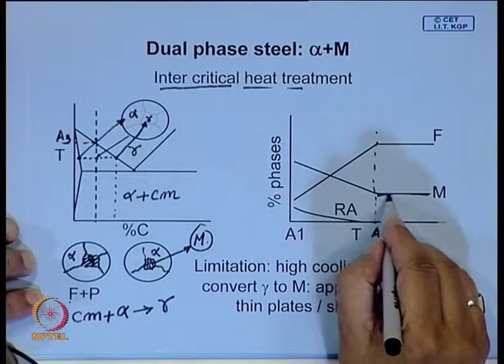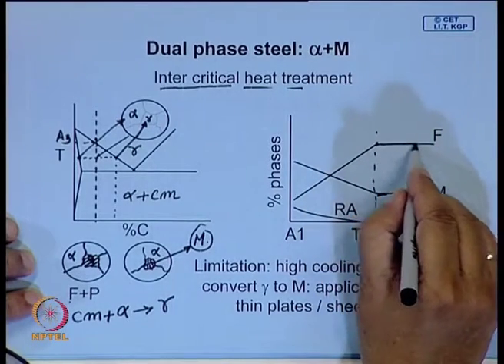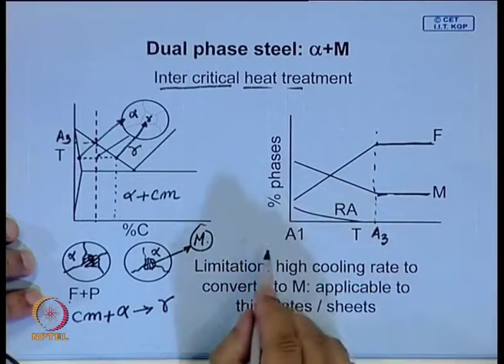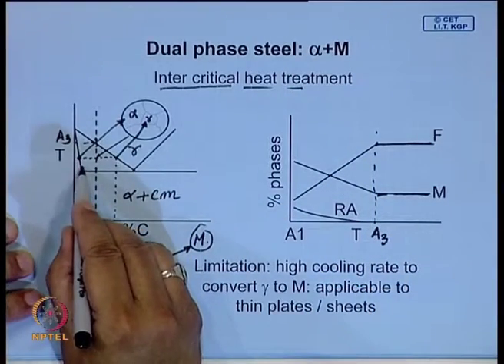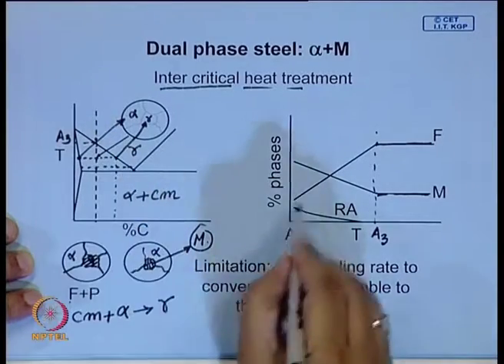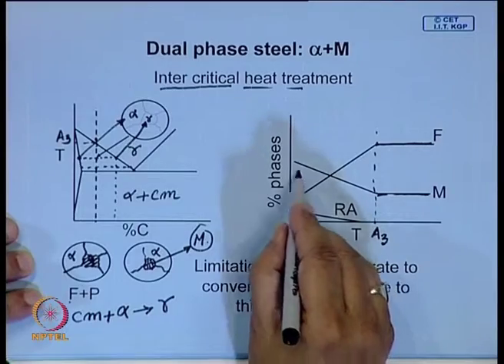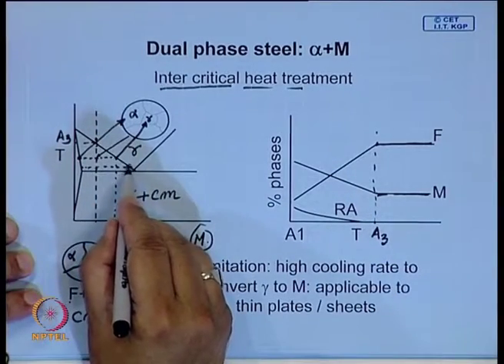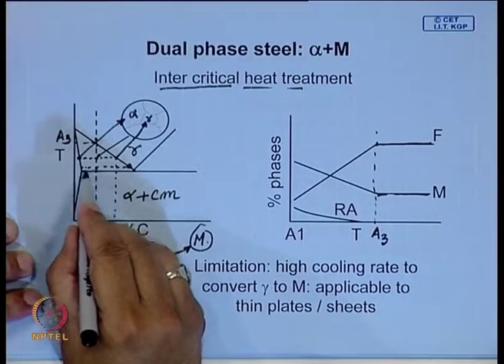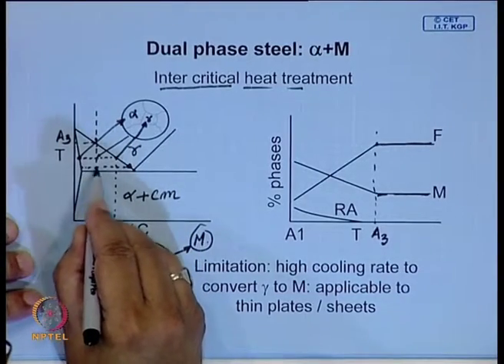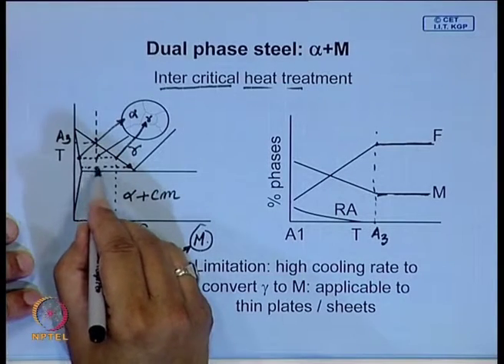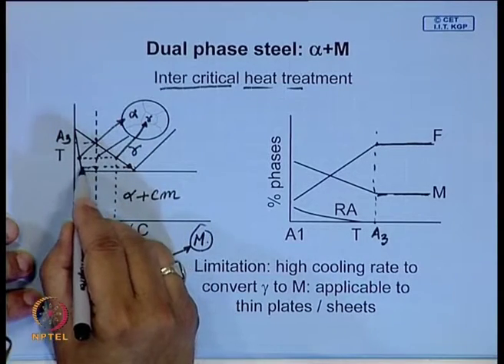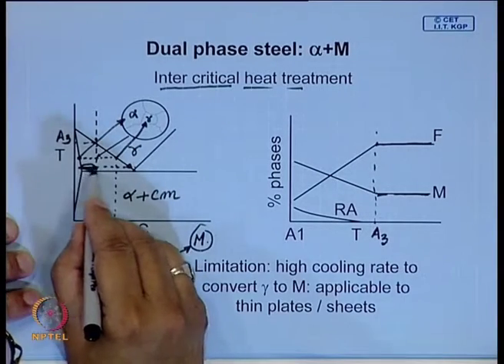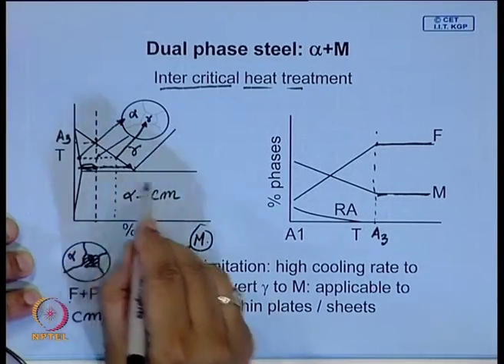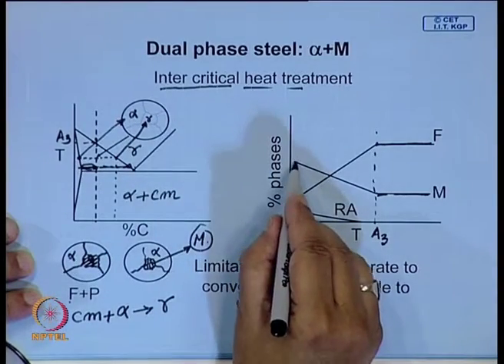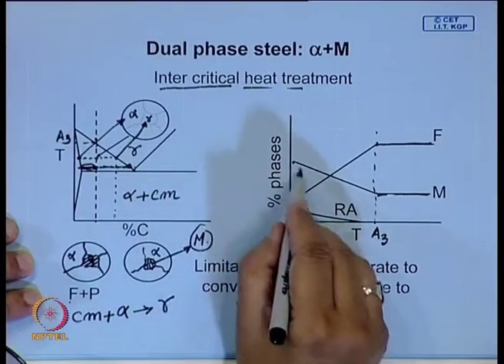You have a very small amount of martensite and it may have mostly ferrite. This is the percentage phase. Whereas, if your intercritical heat treatment is given here, then you are likely to have that amount of austenite here, which will be proportional to this line. The amount of ferrite is this, and this is the martensite. So, this will be that equilibrium amount.